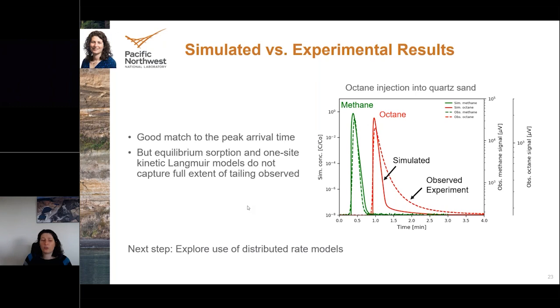We think this is due to the heterogeneous interaction with the solid surface. There are a lot of different active sites, and the gas might be adsorbing at different rates. And so our next steps are to explore the use of distributed rate models that could better capture this heterogeneity.